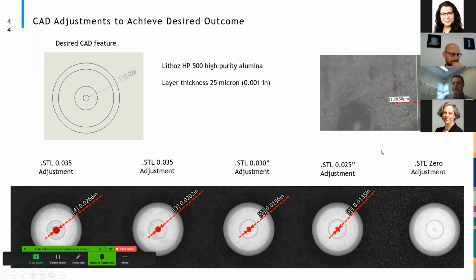By a 5 thousandths of an inch adjustment in size, we achieved our first clearance hole of 13 thousandths of an inch through the component, visible all the way from top to bottom. It wasn't until we reached a 15 thousandths oversize based on the CAD file that we achieved our desired 20 thousandths of an inch in diameter. This was measured at both the top and the bottom, and it was very consistent across the measurement.